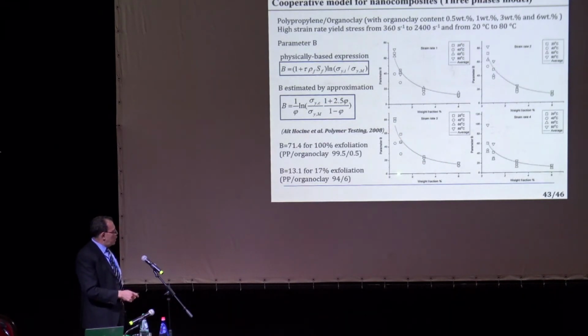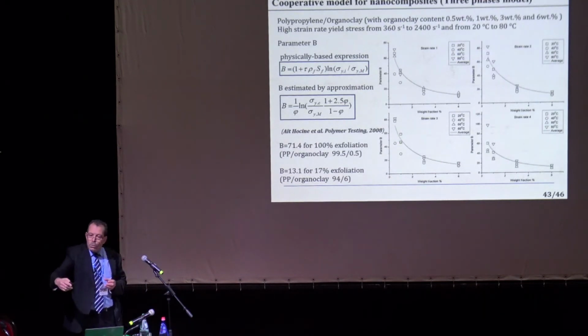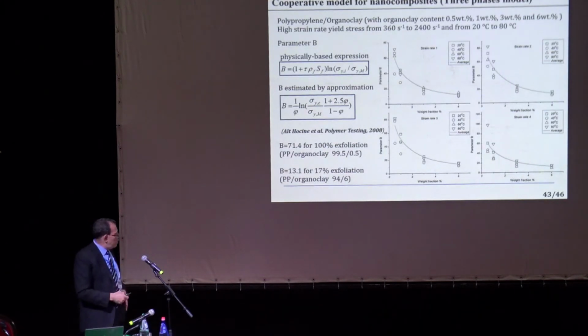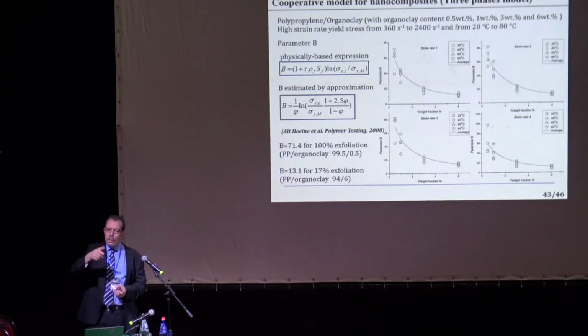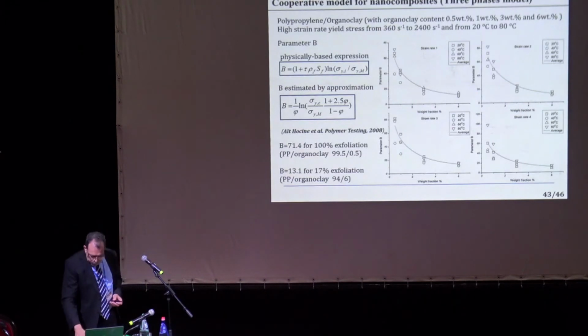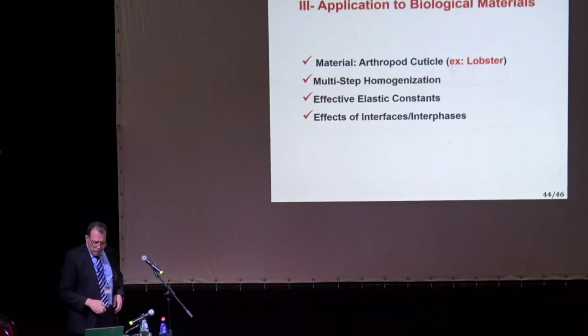It is high when the weight percent is very low, which means here we have exfoliation. But if you go to a higher load of the fillers, you don't get everything exfoliated. You have intercalation, but you also have particles that did not intercalate, did not exfoliate at all. That means that you can use this to estimate the amount of exfoliation. So that's what we did here. For this case here, B, we find 71. We linked it to the exfoliation 100%. If we have this value here, we got about 17%. So we can use this relationship to estimate the amount of exfoliation.